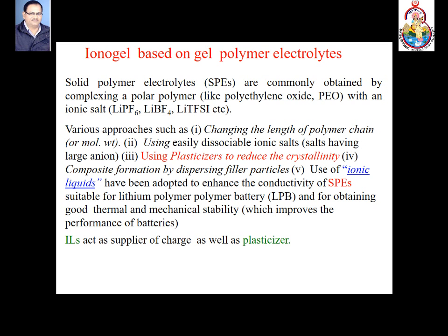Ionogels can be obtained by dispersing ionic liquid or ionic liquid salt solution in polymer matrices using high molecular weight polymers like polyethylene oxide, PVDF-HFP, etc. The ionic conductivity of these polymer electrolytes is very low. Therefore, for their application in rechargeable batteries, different approaches have been adopted to enhance their conductivity, for example, using high molecular weight polymers, nanofillers, or plasticizers. Organic ionic liquids have emerged as a novel class of plasticizers which, besides enhancing the conductivity of polymer matrices suitable for fabricating lithium batteries, offer safety considerations.